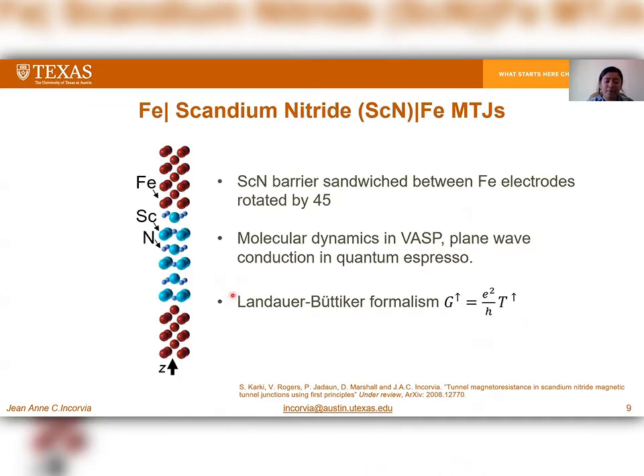Now moving forward to Fe/ScN junctions. We created several ScN junction layer systems. We did 3, 5, 6, 7, and 8 layers sandwiched between two ferromagnetic Fe electrodes. The scandium nitride region was rotated by 45 degrees so as to match it with the lattice constant of iron. The molecular dynamics was done in VASP and the plane wave conduction in Quantum Espresso. Quantum Espresso uses a Landauer formalism that depends on the transmission probability and gives you the conductance value.